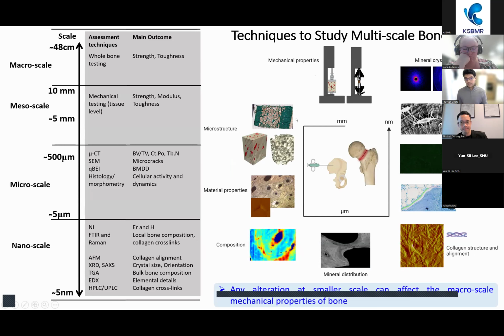I have used some of these techniques. For example, for mechanical property, we can do a compression test, bending, or tensile test. Microstructural analysis can be done in 2D with histomorphometry or in 3D with microCT. Material property can be tested with nano indentation, micro indentation, and nowadays in vivo material property testing is also possible with OsteoProbe. Compositional analysis can be done with spectroscopic techniques, for example FTIR, Fourier transform infrared spectroscopy, or Raman spectroscopy. Mineral distribution we can study with QBEI, quantitative backscattered electron imaging, where we can see the concentration of calcium over the bone surface. Likewise, there are other techniques available.